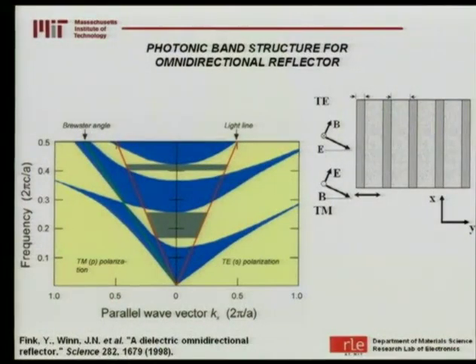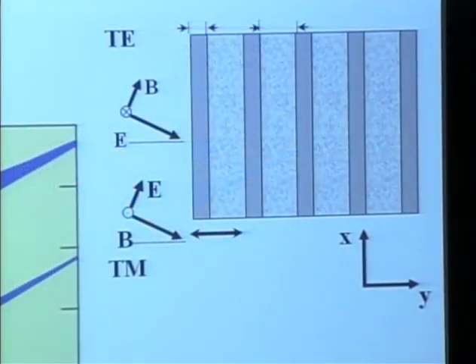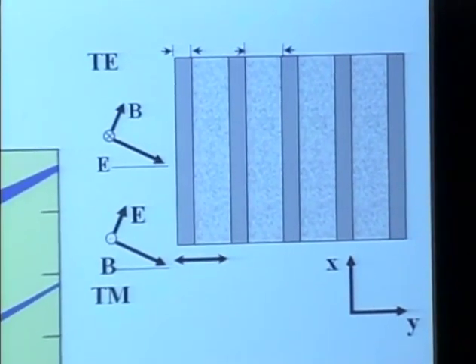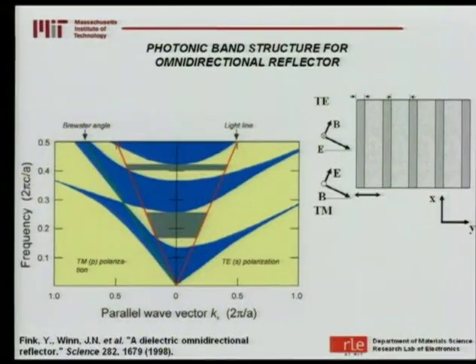Now, if you were able to produce such a surface, you could then use it to contain light. Depending on the geometry of your surface, you could trap light in a volume or along the length of a fiber. And that was the very first discovery that we made, which was that, if engineered correctly, you could in fact produce this perfect reflection from a simple multi-layer dielectric. Now, obviously, the layers here are a fraction of a wavelength of light, and that poses considerable fabrication challenges when we scale this up to very long length scales.